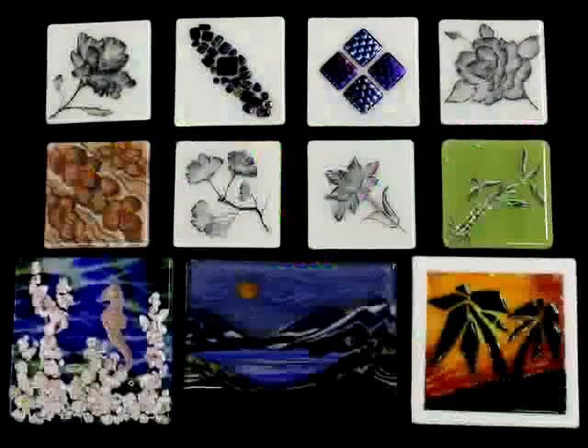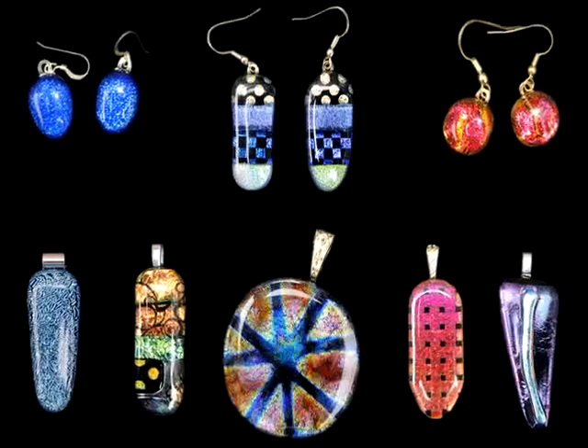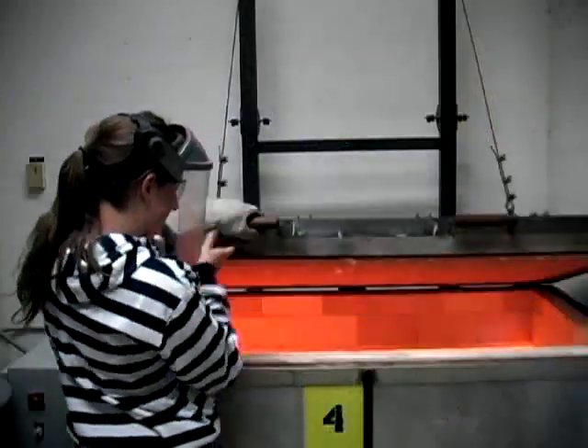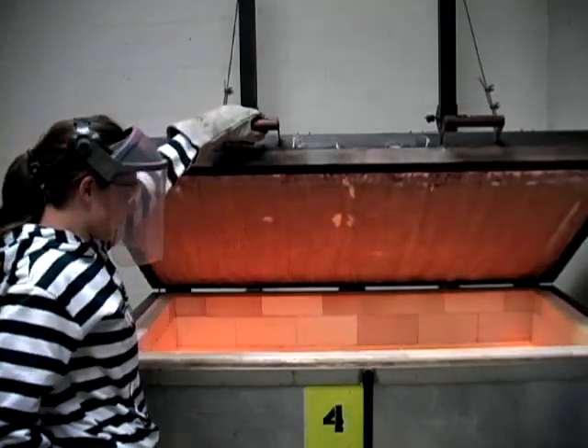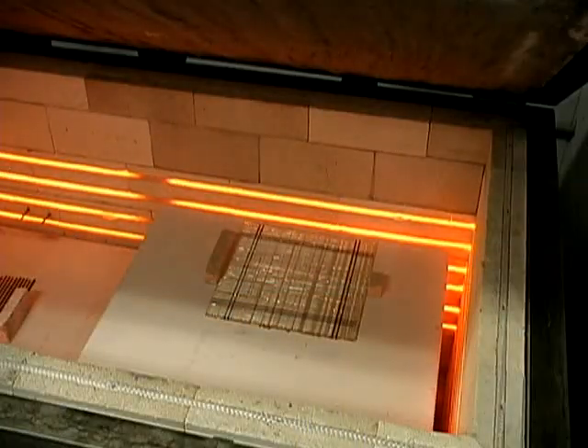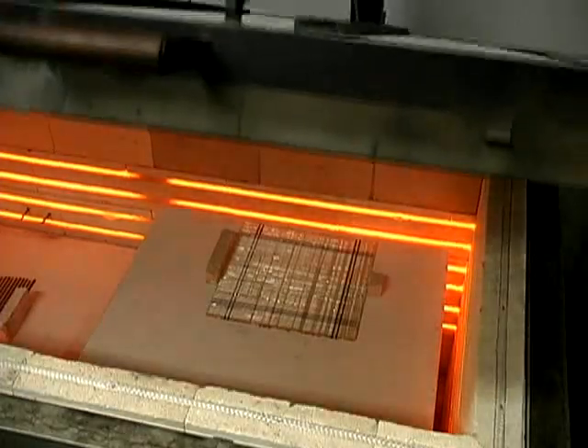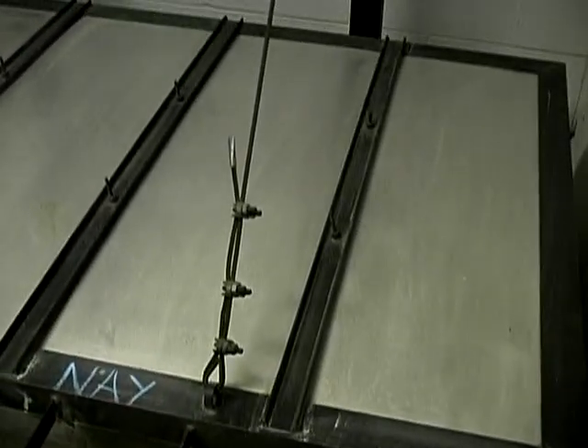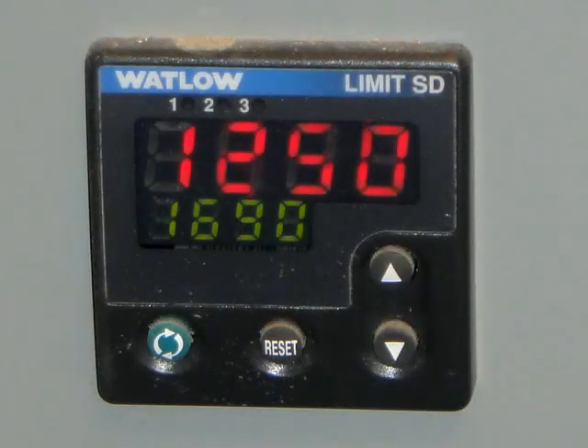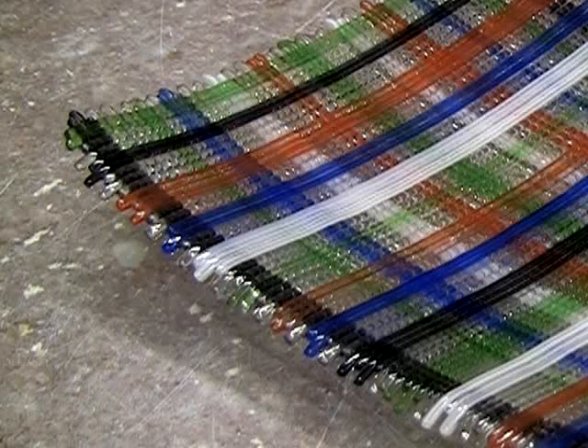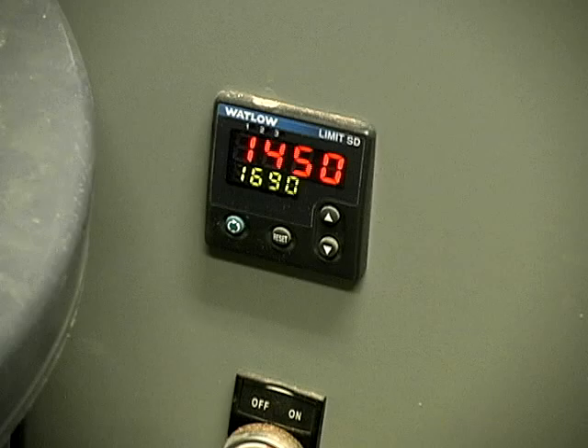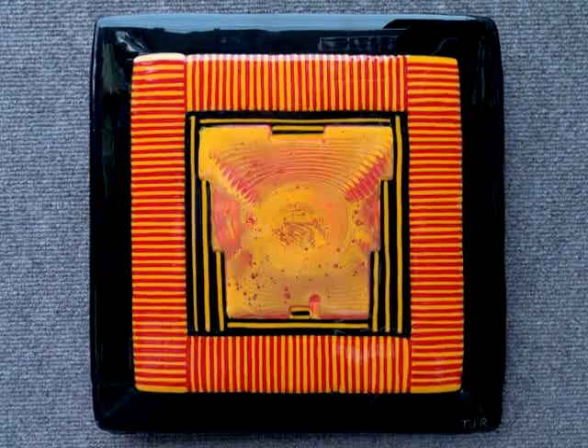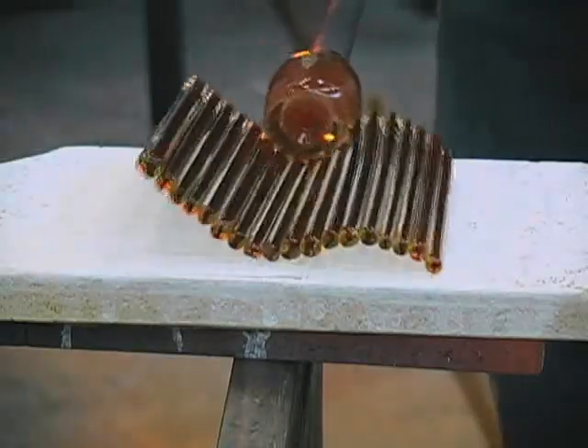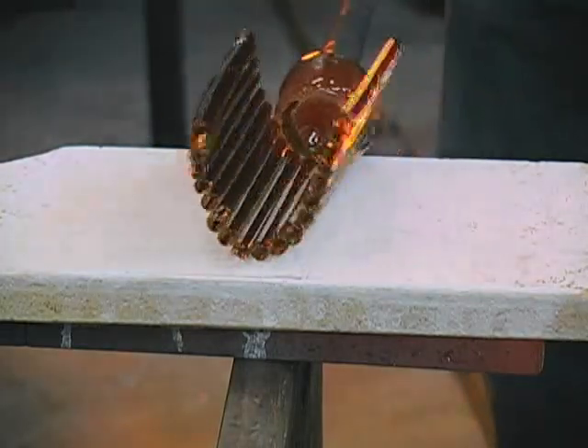Fused glass objects, such as vessels, tiles, and jewelry, are created by heating glass layers in a kiln until they bond. The temperature required to fuse glass is much lower than that used for glass blowing, between 1,250 and 1,325 degrees for tack fusing, and 1,450 degrees for full fusing. The hot fused glass can be worked into shapes with a variety of tools.